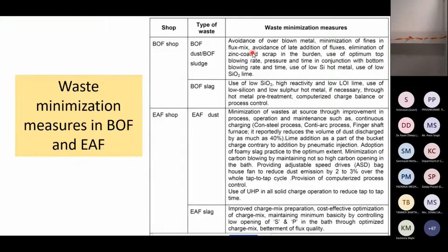Same thing for the electric arc furnace also: minimization of waste at source through improvement in process operation and maintenance, such as continuous charging. So you have to adopt continuous and not intermittent charging. We have to go for continuous small-quantity charging happening continuously, so that this reaction is going to be continuous. Lime addition is a part of the bucket charge, contrary to addition by pneumatic addition or injection. So whatever lime addition is there, it's with the bucket.